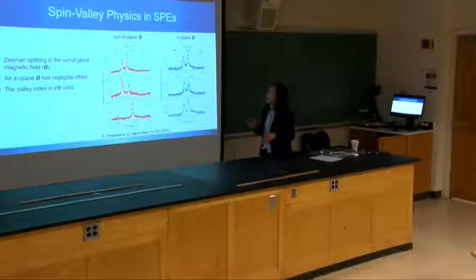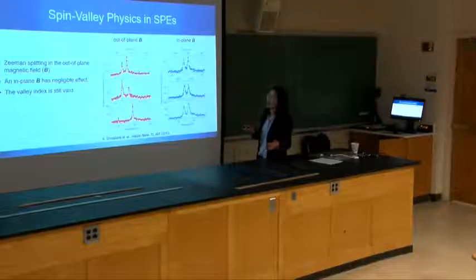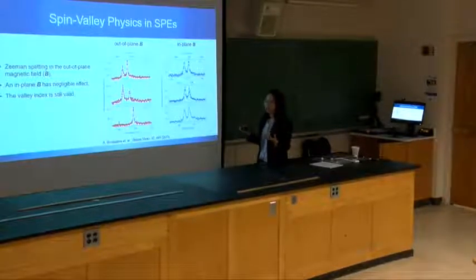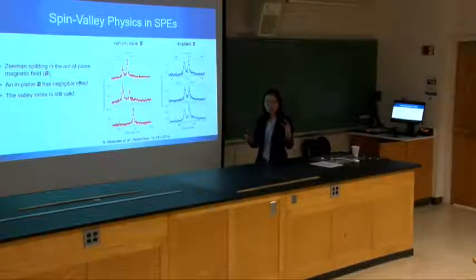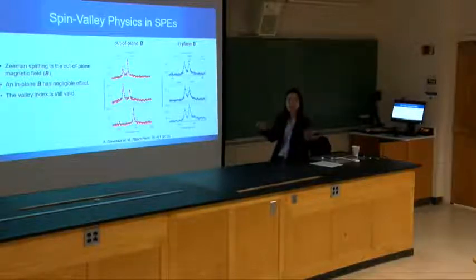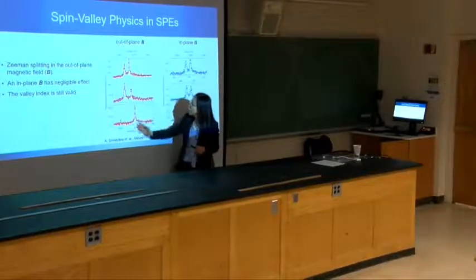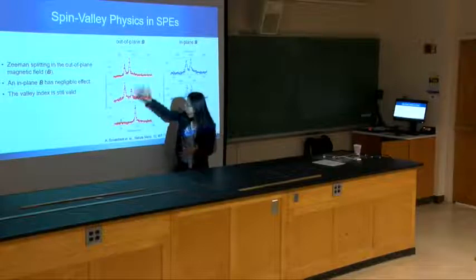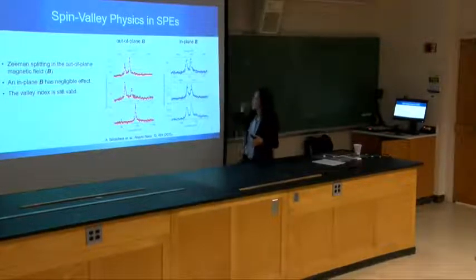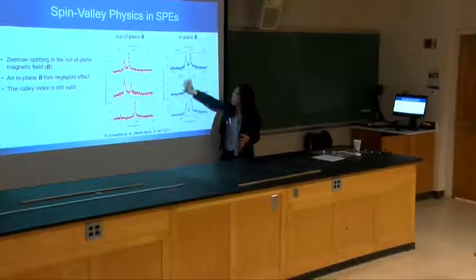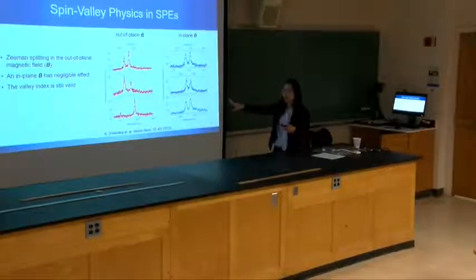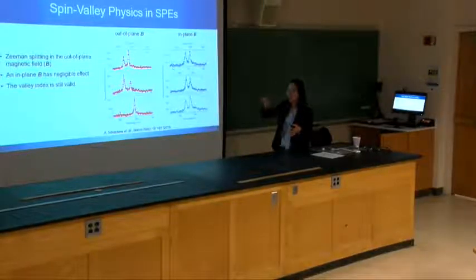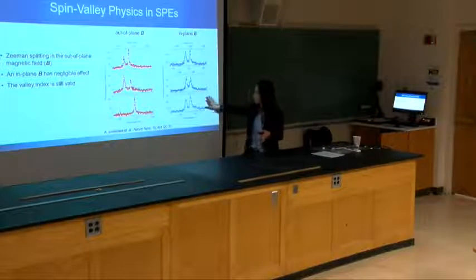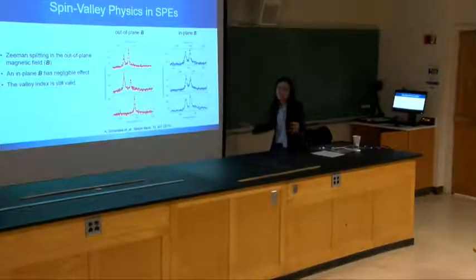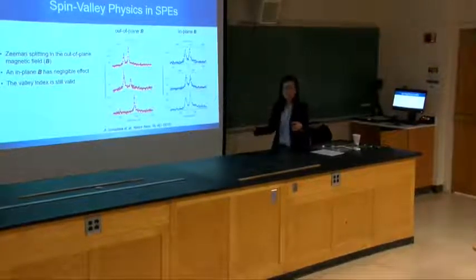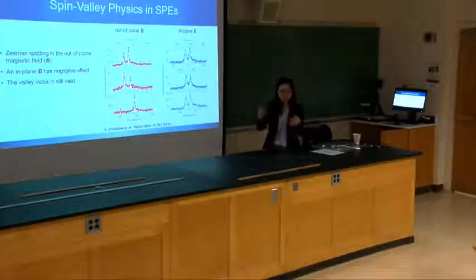The amazing thing about these single photon emitters embedded in the monolayer is that they inherit these properties from the host, unlike the NV center. The NV center itself does not inherit so much property from the diamond. As you can see, if we apply an out-of-plane magnetic field, the emission from the single photon emitter changes. But if we apply an in-plane magnetic field, even up to 3 tesla here, we don't see much difference. That's because an in-plane magnetic field like 3 tesla is too small compared to the 400 milli electron volt splitting. That's why there's almost no difference. So this is evidence that the single photon emitter, or the localized exciton, inherits the electronic structure from the host monolayer.